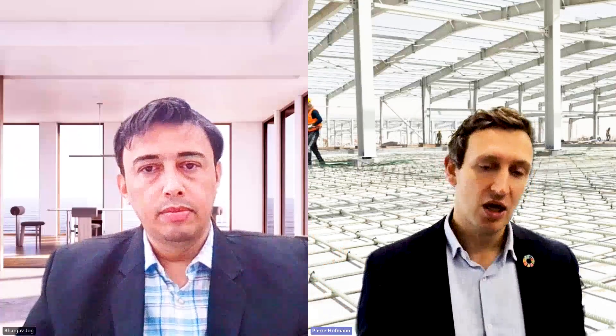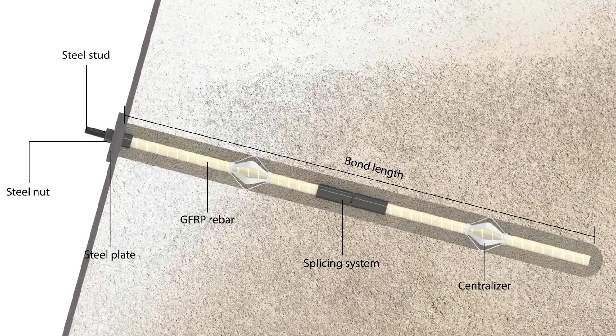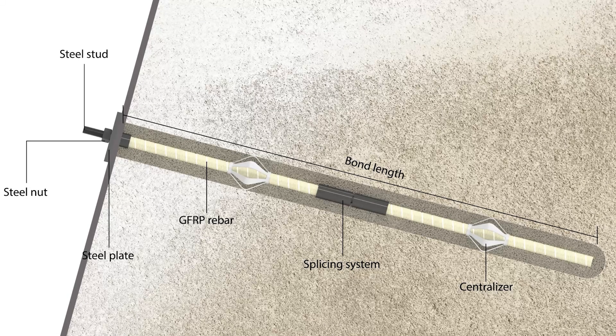It's been published in several papers that, thanks to the surrounding material deforming, the GFRP will not be experiencing a pure shear load — there will be a significant tensile contribution. The tensile properties of GFRP at 90 degrees is around 350 MPa based on actual data, and at a different angle, it can approach the ultimate tensile strength. GFRP can reach 900-plus MPa when there's a shear angle of around 45 degrees, thanks to the contribution of the cementitious material.